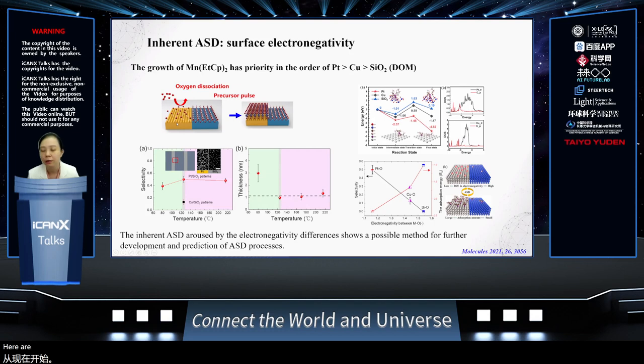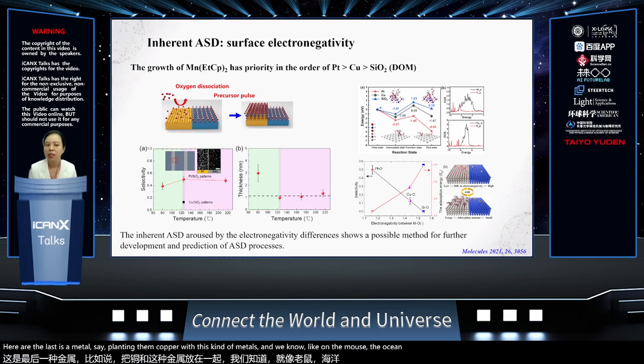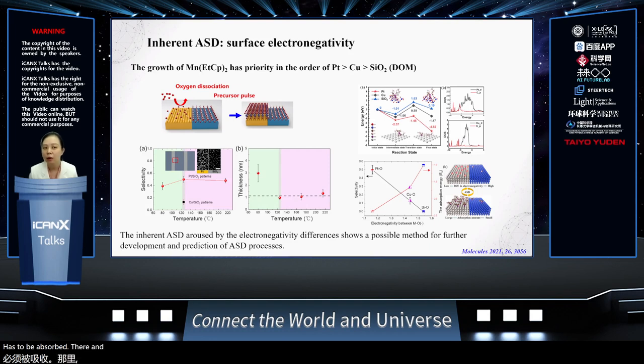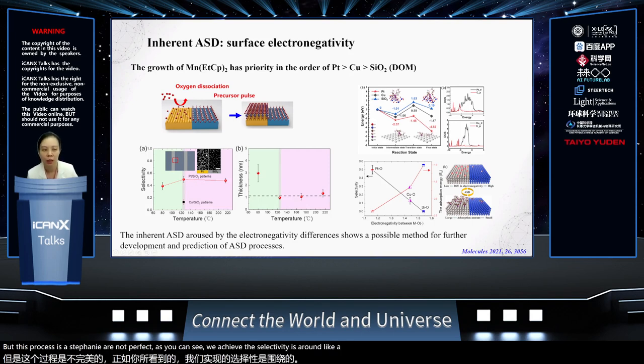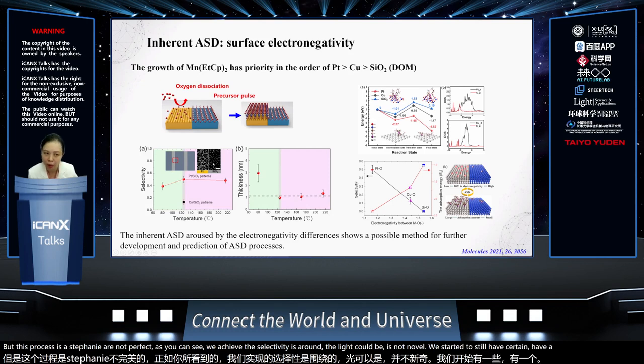So here, the left is a metal, say platinum, copper, or these kinds of metals. And we know that on the metals, oxygen tends to be absorbed there. And most of these noble metals tend to dissociate oxygen very well. We utilize this phenomenon, let the oxygen dissociate, and then let the reaction happen. So relatively easily, we'll be able to grow the materials on the metal side, but not too much on the oxide, because we rely on the initial nucleation there. But this process is definitely not perfect. As you can see, we achieve selectivities around this level. We definitely still have certain growth on the oxide part.